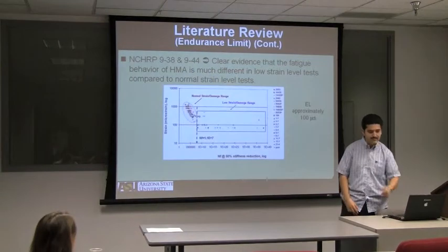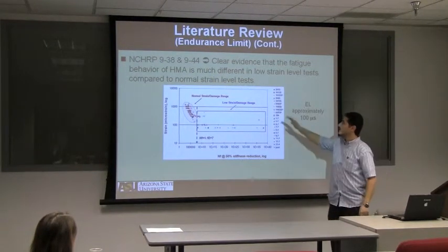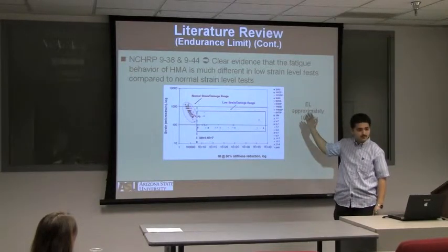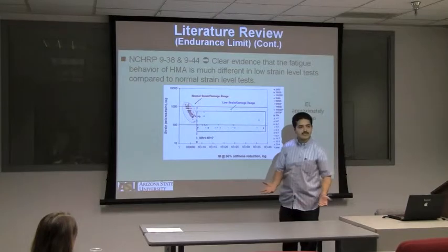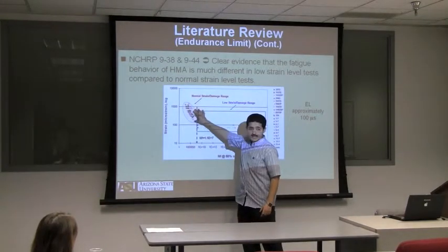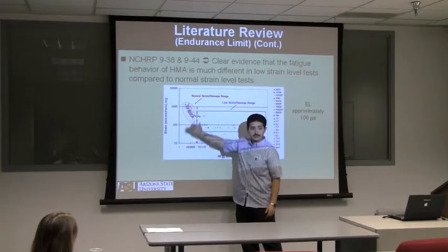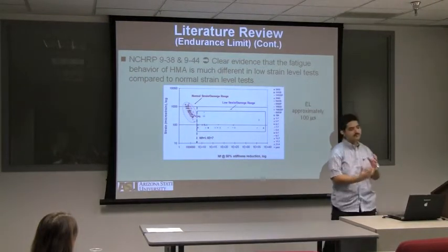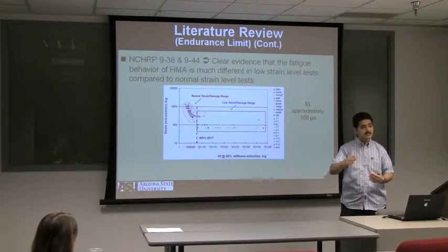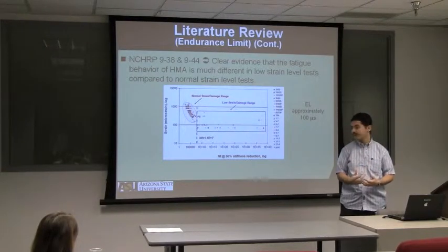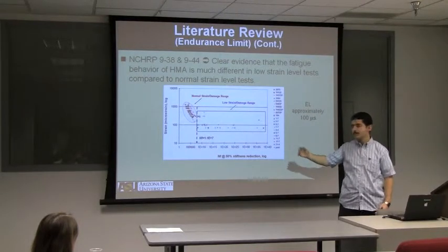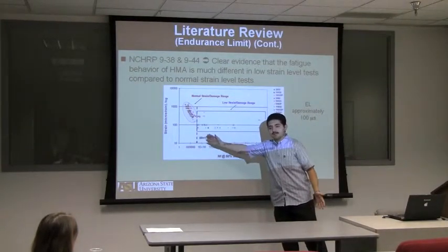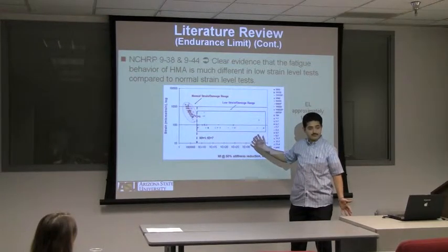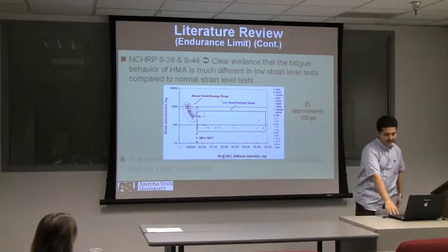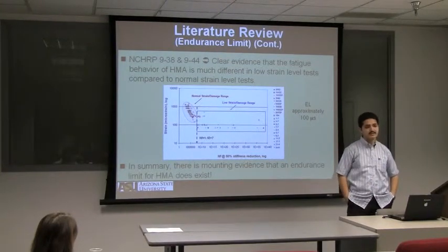And when I say that, what happens in these two projects is there is something called normal strain levels or low strain levels. So in the regular fatigue analysis that we usually do, we apply very high strains that range, let's say, from 200 to 1,000 microstrains. But what these two projects did, once they decreased this amount of strain or deformation on the sample to 70 microstrains or 100 microstrains, the sample wouldn't fail even after 50 million cycles. 50 million cycles. And they came up with a summary that there is mounting evidence that there is an endurance limit for the hot mix asphalt.